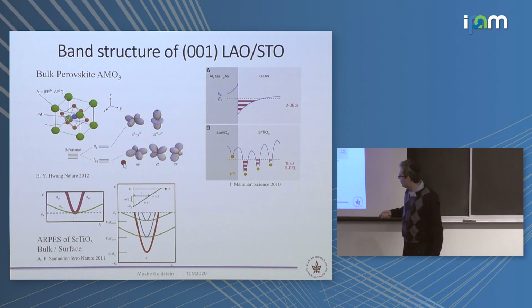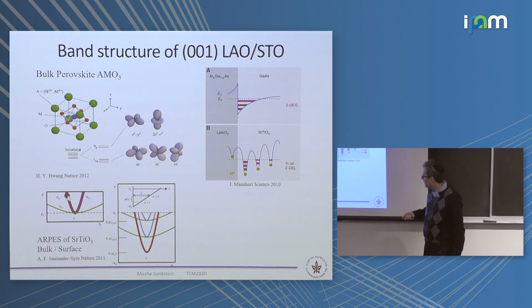So as I told you, what are going to play a role are those t2g orbitals. And in the bulk, they are degenerate, and there are some couplings that break this degeneracy. And when you have this interface, then you basically have confinement. And then if the confinement is in the z direction, the xy band, which has higher mass in z, the confinement direction, will be lower in energy, and the other bands are going to be higher in energy. So your first band is going to be xy, and it's going to have actually low mass in the direction of xy, so in the propagation directions, and then will come the other bands which have low mass in z, but actually they will have higher mass along the other directions.